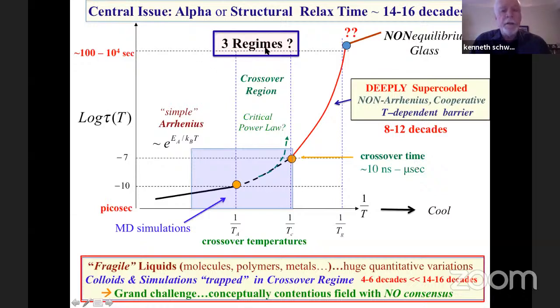People often have talked about that there's 3 regimes here. At high temperature, there's a straight behavior, which is an Arrhenius regime, although it's not really simple in the sense of being understood. At low temperature, you may have 8 to 12 orders of magnitude of strongly non-Arrhenius behavior. We call that the deeply supercooled regime. And you can think of it in the sense that the barrier is temperature dependent and growing. Below TG, you fall out of equilibrium, and what happens in equilibrium as you go further up is not well understood. In between, there's a crossover regime that different people think different ways about. One idea about it is that there could be a critical power law in here. I'll discuss this at some detail shortly. Now, if you believe in these 3 regimes, then you have 2 crossover temperatures and 2 crossover times, and it's interesting to know about them.